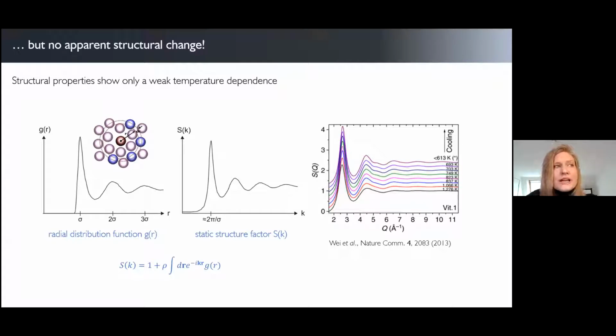So if you look at the structure of a disordered system, like a liquid or a glass, there are different ways to quantify that structure. But one of the most simple ways to quantify structures is to look at something called the radial distribution function, g(r). So this function simply tells you, given that there's one particle here, what's the likelihood to find another particle some distance r away from that particle on average. So this is a two-particle correlation function that in a disordered system typically looks something like this.